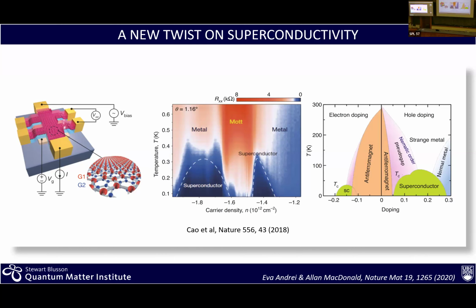Well, I know it's not your work. First of all, the scales are not comparable. Nowadays, this particular phase diagram shows additional complexity. I think it depends a lot on the quality of the device you obtain. While this comparison looks very intriguing, in the most recent version of this phase diagram, you actually see that you get additional insulating phases. So I think you now can achieve clean insulating behavior here, but then you also see other differences, which are additional insulating phases at different doping levels. So there is quite a bit of complexity now coming out of here.